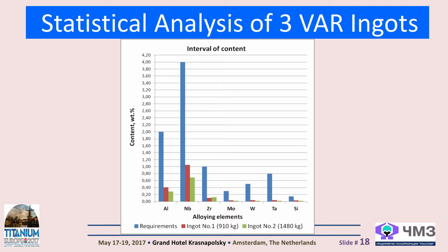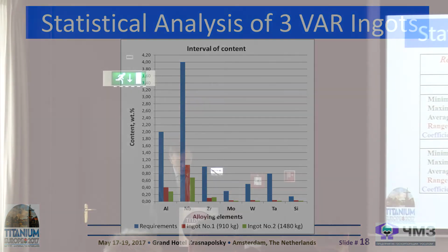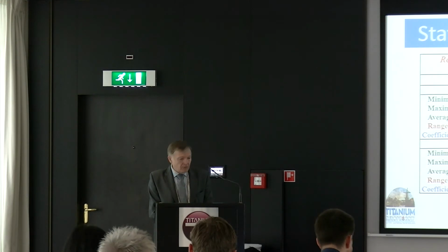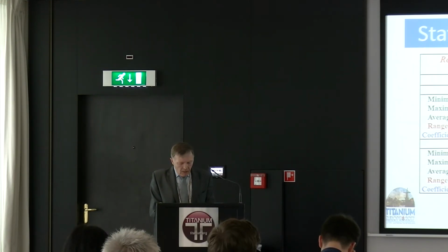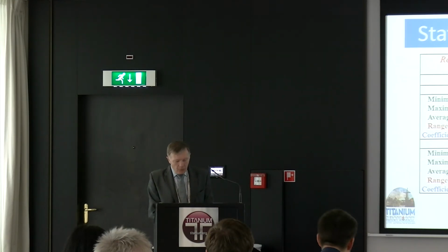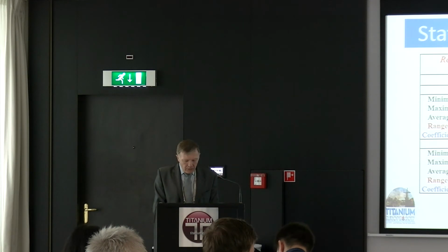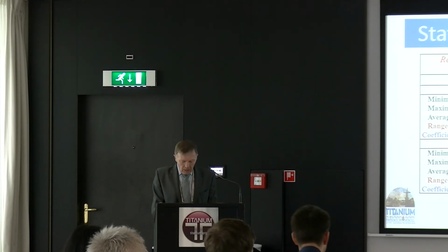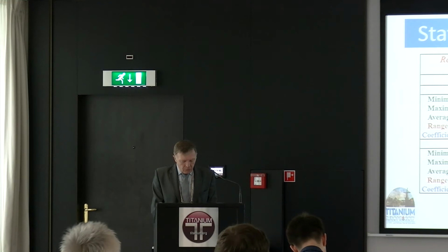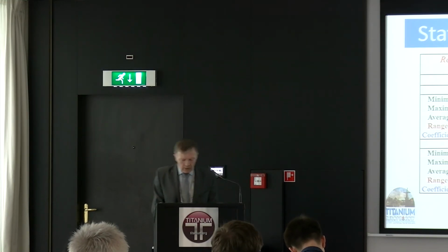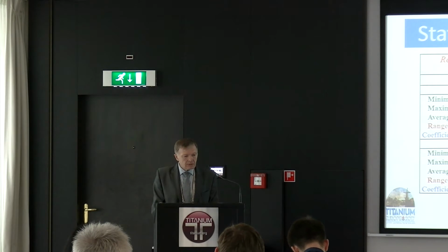The largest values of the coefficient of variation are noted at silicon, but with a planned transition to a more accurate determination of the silicon content to a thousandth of a percent, one should expect a decrease of the coefficient of variation. At the same time, the least value of the coefficient of variation, 0.9, has niobium with the largest content in the alloy. It is important to note the high distribution uniformity of the most refractory alloying components, tungsten and tantalum.